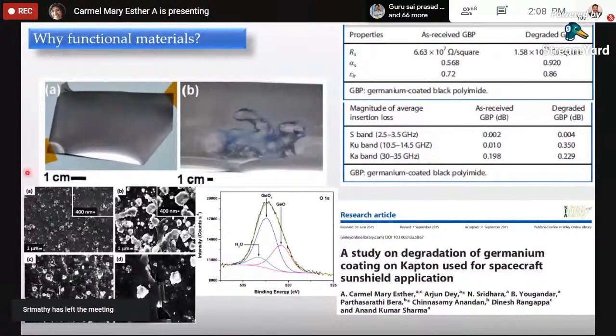For example, if we take freshly prepared germanium-coated black polyimide, it already has the required thermal, optical, absorptance, and sheet resistance behavior, and it is also highly transparent. But what we faced in ground storage, once we exposed this germanium-coated black polyimide to the normal ambient environment, is that it starts degrading, meaning it absorbs oxygen from the air and is oxidized. Initially the degradation starts microscopically, with micro cracks, but later it degrades macroscopically, and the degraded germanium-coated black polyimide does not serve what we required. Especially the sheet resistance becomes highly insulating, and the thermo-optical properties also change. It is not transparent anymore.